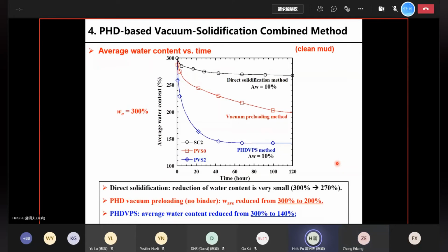So this is average water content versus time for different treatment methods. The black curve on top is the direct solidification method. As you can see, the reduction of water content is very small. It went from 300% to 270%. That's because some water is consumed by the cement. And in the middle, the red curve is for the vacuum preloading method. In this case, there's no binder, but there is a vacuum that sucked out the water, and because of that, the water content reduced more significantly from initially 300% to roughly 200%. So the dewatering efficiency is better than the direct solidification method above here.